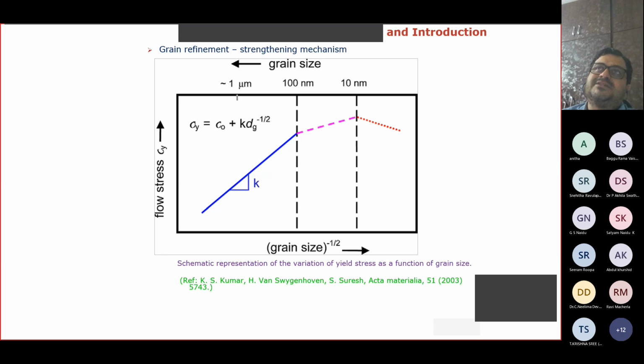And subsequently, several scientists or academicians have also realized this type of dependence in various other materials as well. So to respect the initial observers of this phenomenon, the whole scientific part of this grain size dependence of the flow stress is called the Hall-Petch effect or Hall-Petch equation, which is sigma y equal to sigma naught plus k into d power minus half.